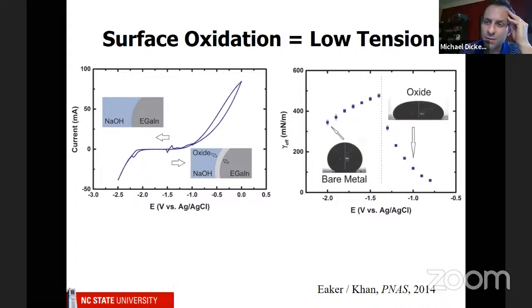But when that happens, the surface tension doesn't change very much. It changes just a little bit. And then we keep applying a voltage, and at some point you see that it goes way up. And where we see around 0 surface tension is right around here. So the point is that the oxide initially deposits, but it's not until higher potentials that we start to see it really form those instabilities. But you'll notice that when the oxide does first form, the tension drops, and then it drops some more, and it drops some more, and it drops some more. And frankly, we don't know why.